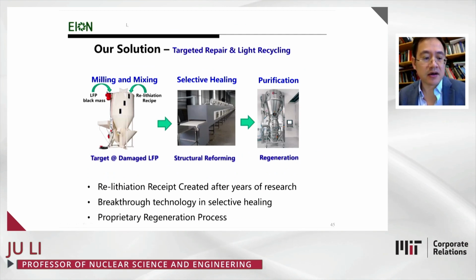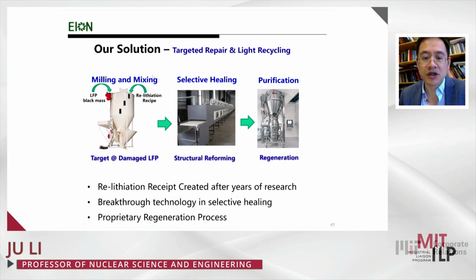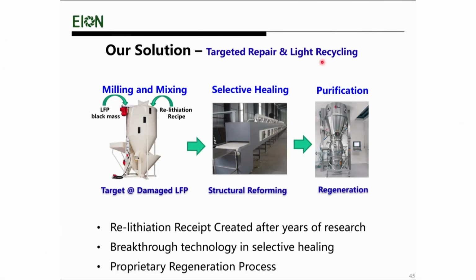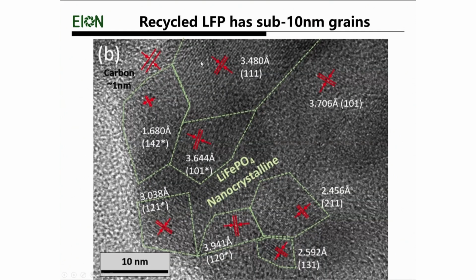So we have a new company called E-ion, which have developed this light recycling technology where we add lithium to the black mass, as well as some other chemicals, and we do a selective, very intense but rapid process to regenerate the lithium iron phosphate cathode. So this is the microstructure of the recycled LFP, where we actually form this very fine sub-10 nanometer grains, which is recrystallized lithium iron phosphate.